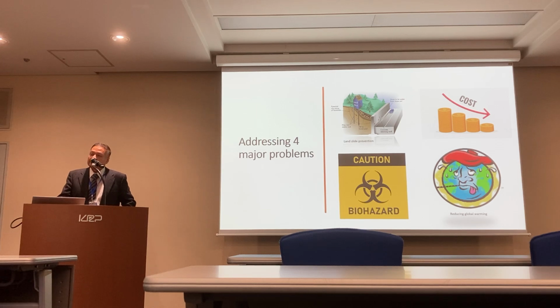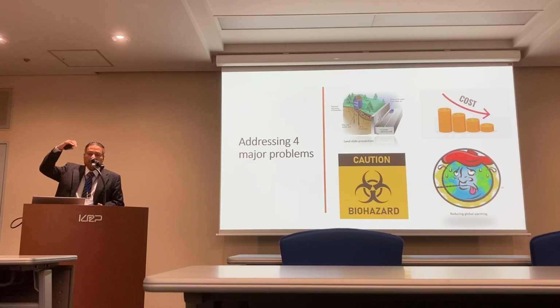I see. So in case of heavy rainfall, like we saw earlier in New Zealand, what is the infiltration capacity? That is a very good question. Actually, it can reduce the permeability of the soil significantly. We checked in the model slope test, and we found that after the biocementation, the water penetration or percolation is very low. So it can increase the geotechnical properties and make it a stronger soil.